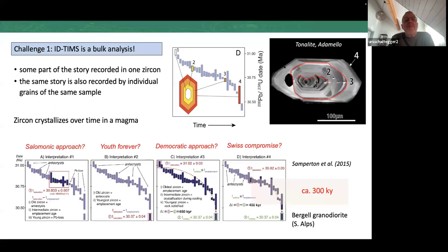Okay. The main challenge for ID-TIMS dating is, of course, that we should never forget, this is a bulk analysis. So we are analyzing a whole grain, despite the fact that we clearly see in this grain 4 distinct growth episodes of this zircon. So this is a core, which is not an inherited core. It's an anticrystic core, which crystallized a few 100,000 years before in a deeper level of the same magmatic system, got resorbed, and then overgrown by zone 2, overgrown by zone 3. The two are again separated by a rounded resorption surface, which is truncating the zoning of 2. And then there is a late overgrowth, which is probably high uranium because it's dark in CL, which is zone 4. So we cannot resolve this.